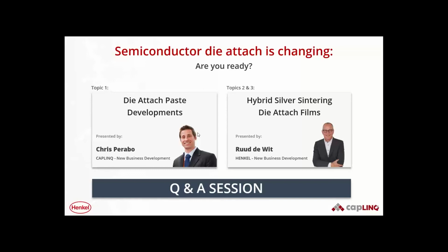So the next question is, concerning the die attach films with silver, how do you cure? Do you sinter them and with or without pressure? For the die attach films with silver. Okay. Now maybe I confused you with the speed of my presentation. I had one section about sintering materials, and maybe I made the change very quickly to the films, which are non-sintering. So maybe I was not clear there. The silver filled conductive die attach films we showed are non-sintering. So they are basically silver stacking.